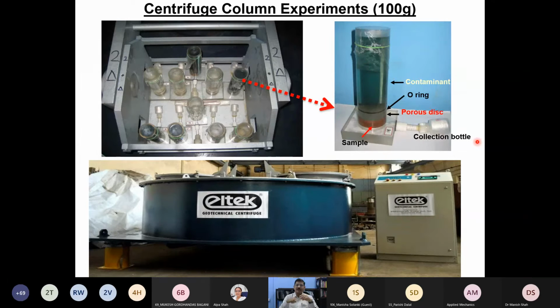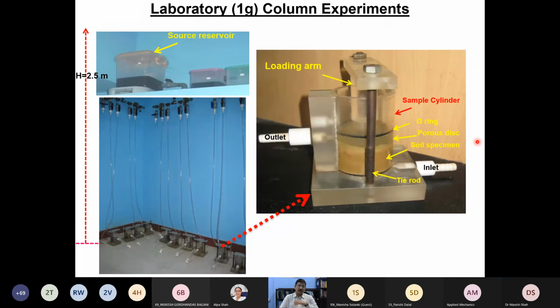If you look at it, this is called the breakthrough curve. Once you have the breakthrough curve, you will get the retardation coefficient. To a certain extent, you can also get the diffusion coefficient. We also conducted experiments at the 1G level. In order to enhance the hydraulic head, we placed the reservoir at the top, around 2.5 meters above the ground surface, and these are all simple column flow-through experiments.